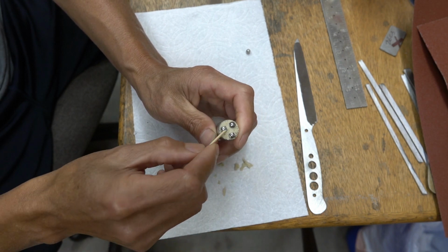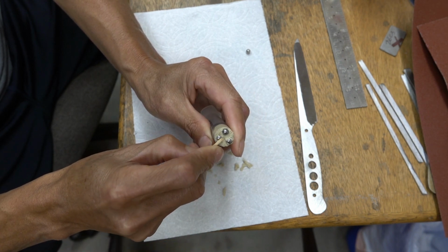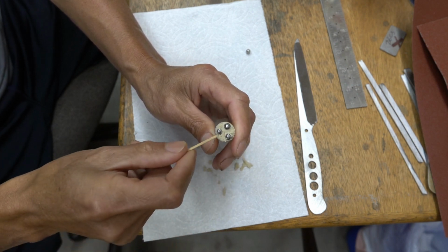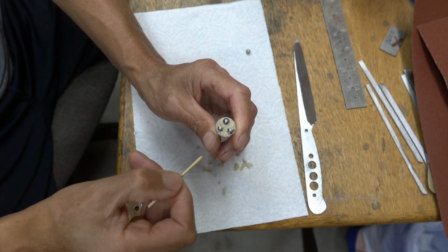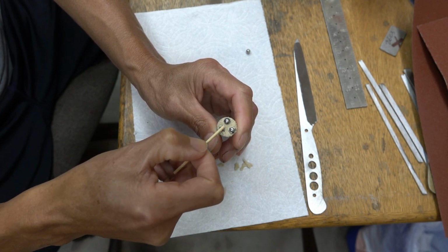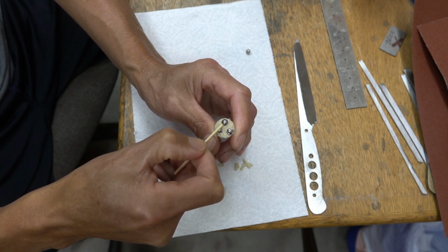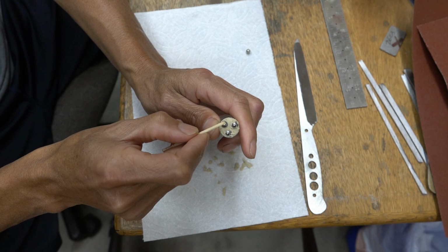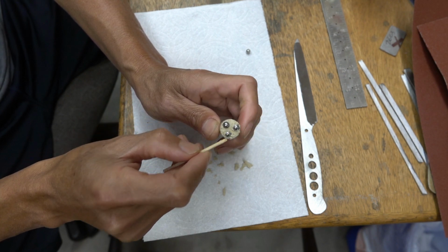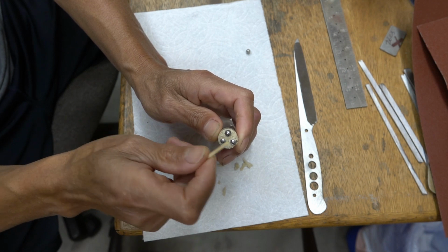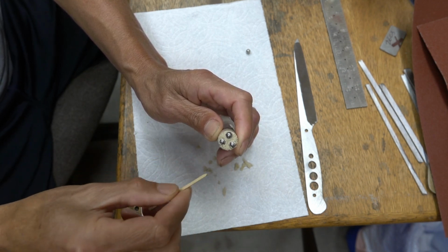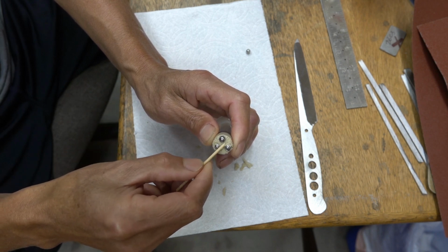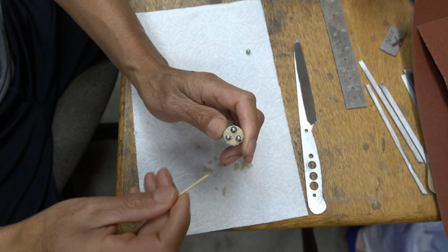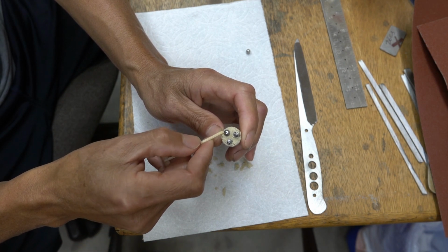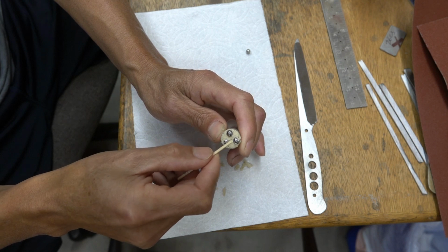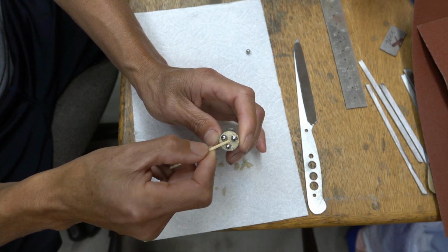I got these two carbides, they are of similar height. Let me push this one down a little bit. Okay. Now, remember the impact of the fixed abrasive, now they will run into this. How strongly embedded this carbide is in the matrix will determine how much it can protrude upward and still be able to withstand the impact of the abrasive. So the result you're going to see is the stronger the matrix, the higher the carbide is allowed to protrude from the surface.